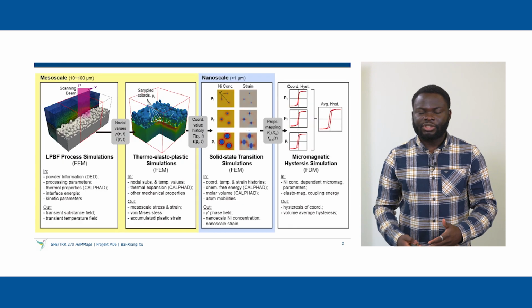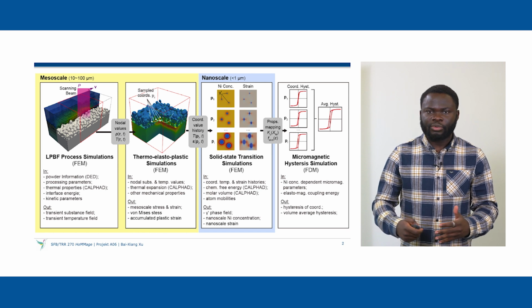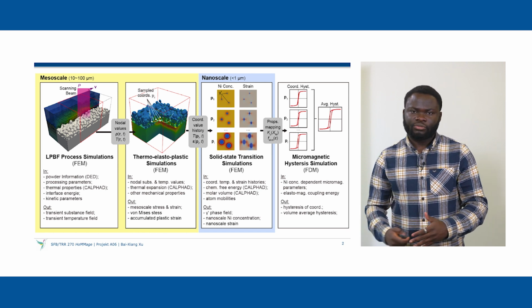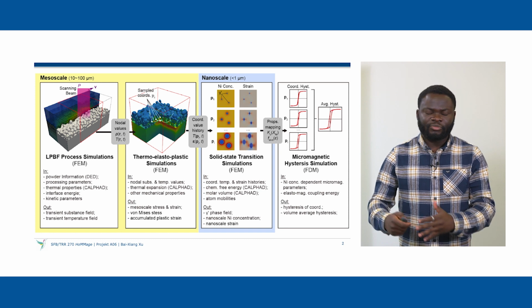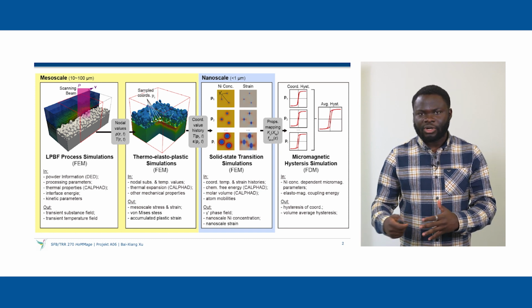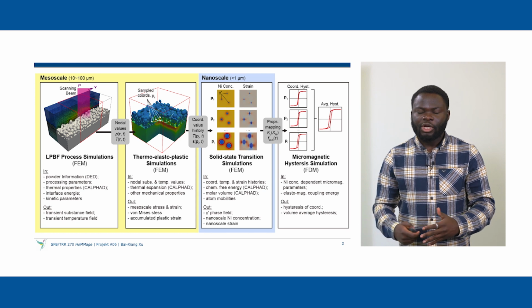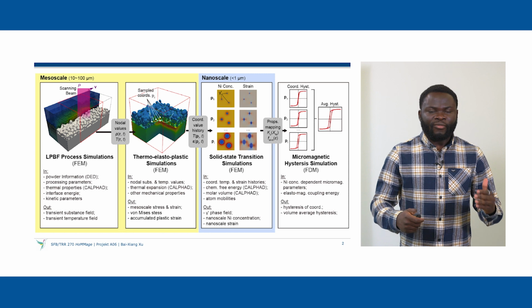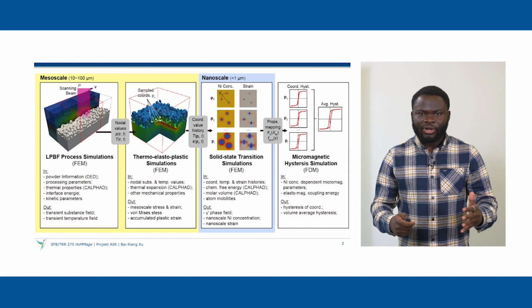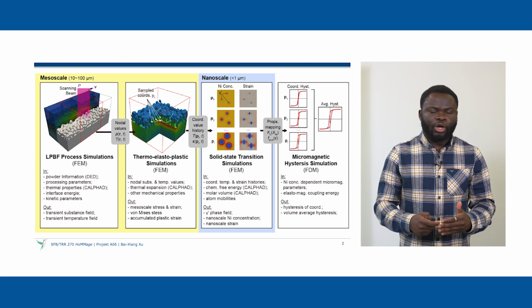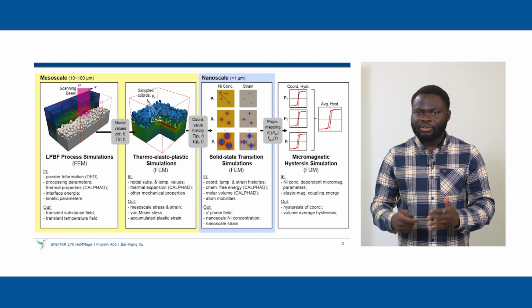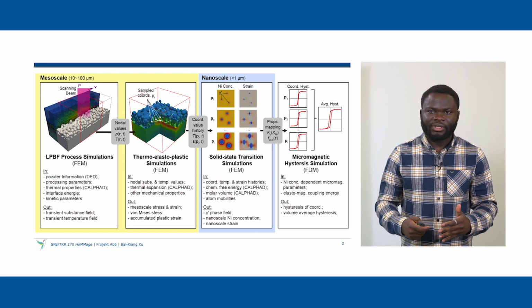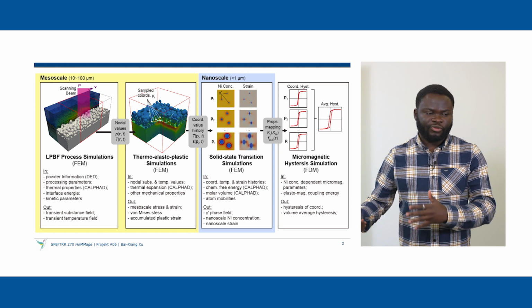So in project A06, what we do is we try to build up a multi-physics, multi-scale modeling and simulation of laser additive manufacturing, and we also collaborate with our colleagues for characterization experiments. For our workflow, first we have laser powder bed process simulations where we take into account processing parameters and material properties. Accompanied by this simulation are thermo-elasto-plastic simulations where we obtain the residual stresses and the plastic strain, as these effects are related to the final magnetic properties of a material.